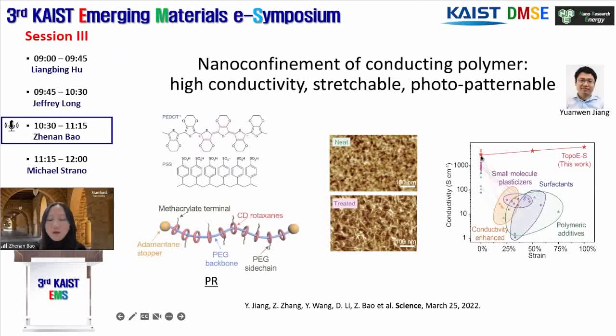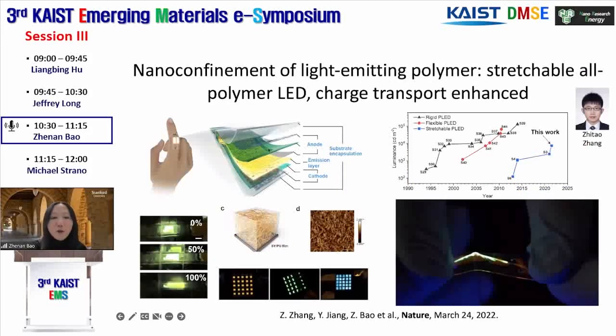And this is the first stretchable polymer conductor that can reach a conductivity at the level of indium tin oxide, and also be transparent at the same time. And even after washing with aqueous solution, it still has a very high conductivity. And furthermore, the nano-confinement effect can be extended to light-emitting polymers. So here, the light-emitting layer consists of a light-emitting polymer and a suitable matrix to induce the nano-confinement effect, but also stretchability at the same time.